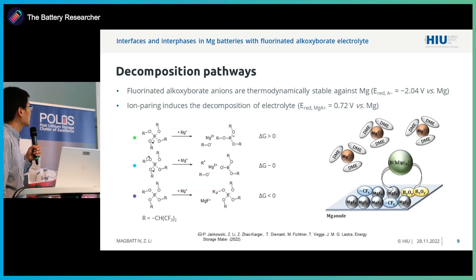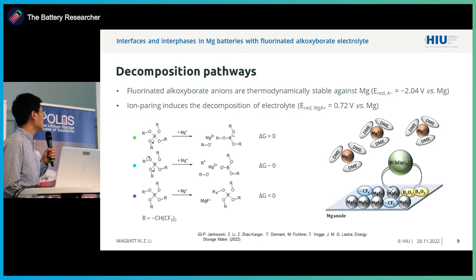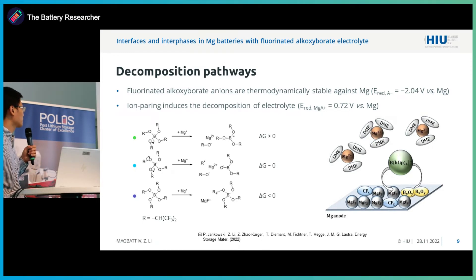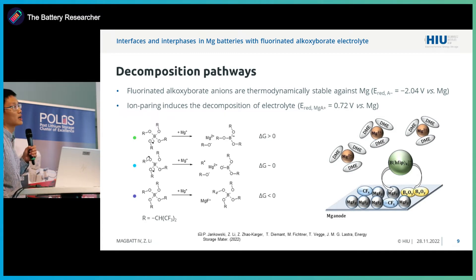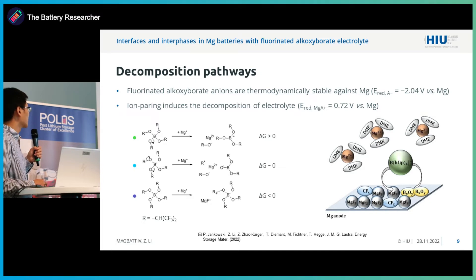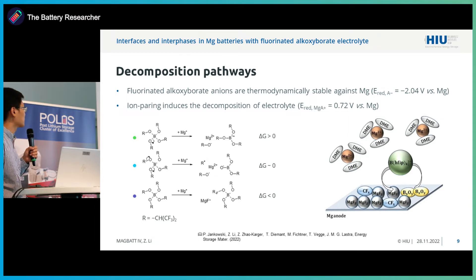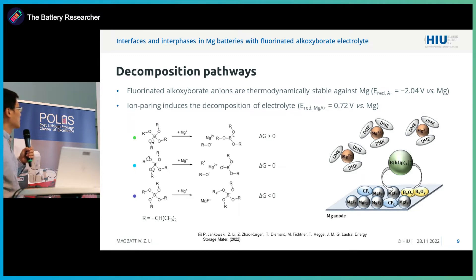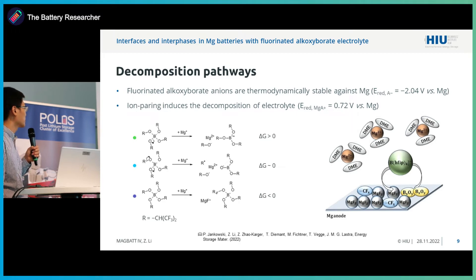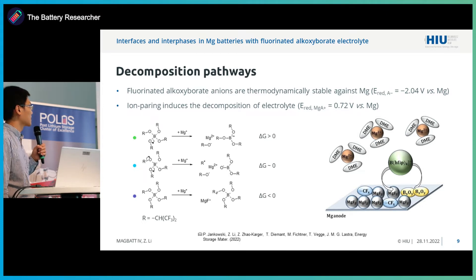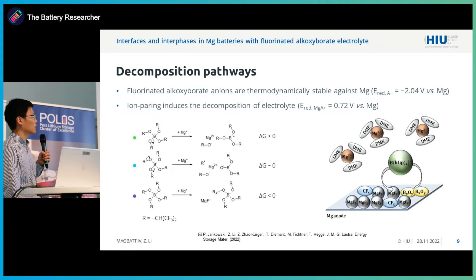We then took a step further to understand the mechanism. Basically, we considered the reductive environment where magnesium accepts one electron, and we considered the breaking of the boron-oxygen bond, the carbon-oxygen bond, and the C-F bond. From the free energy analysis, we see that the last mechanism is more energetically favorable, and also the second one could occur during plating because we normally have some overpotential.